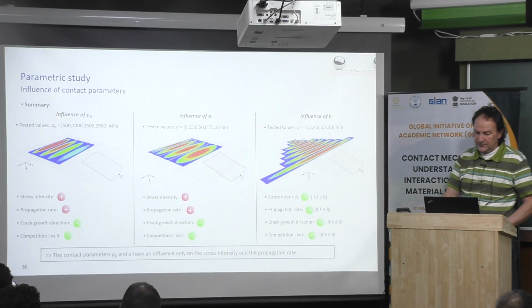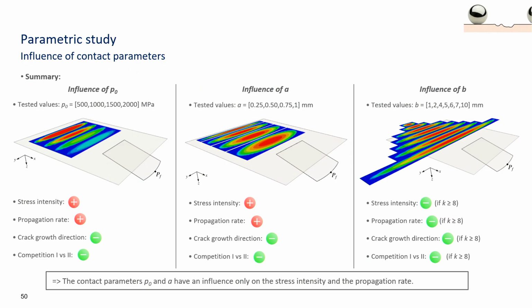Okay, then all these parameters play a role altogether. This is the effect of the size of the contact. Then first, this is the effect of the pressure, then the effect of the semi-minor axis, and the effect of the semi-major axis. Okay. Then, of course, when you increase the maximum contact pressure, you increase the stress intensity factor, you increase the propagation rate, the speed of the crack. You do not affect the crack direction, and you do not affect the change between mode 1 and mode 2.